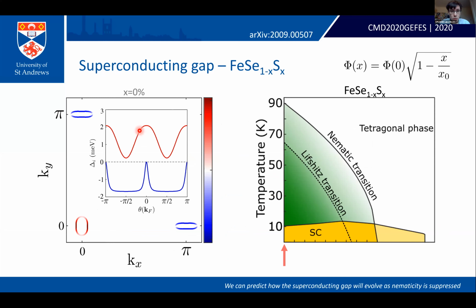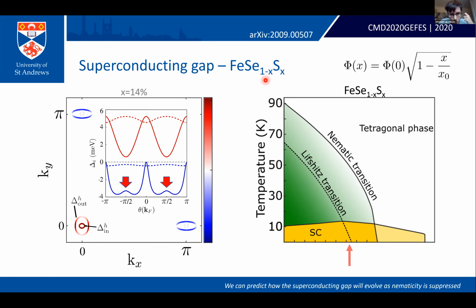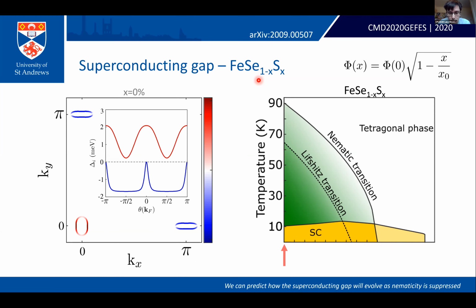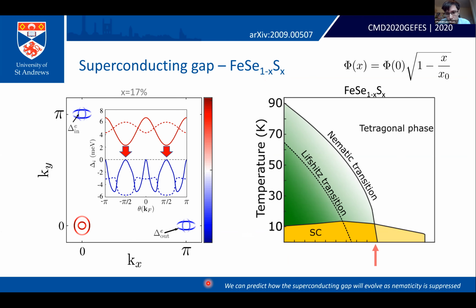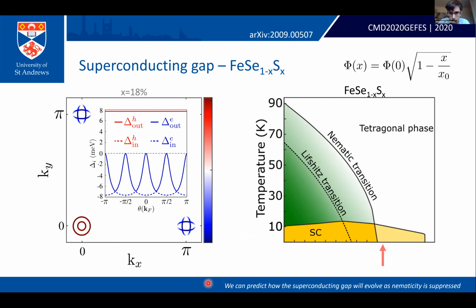Okay, now the superconducting gap structure of iron selenide has been extensively studied within the experimental literature. However, it is not yet known how this momentum dependence of the superconducting gap will evolve as you increase sulfur doping and decrease this nematic transition. And so in our manuscript here, we have made this prediction. I won't go into the details here, but what we expect is that a majority of the changes will occur at this Lifshitz transition, going from a highly C2 symmetric momentum dependence to a more C4-like momentum dependence before going into a fully tetragonal state. And again, this hasn't been experimentally measured yet and will be a good prediction for this dxy nematic scenario.